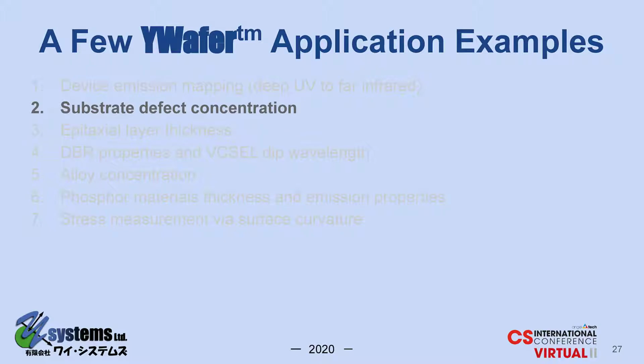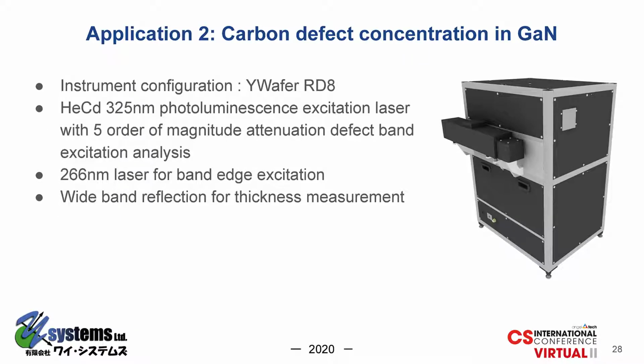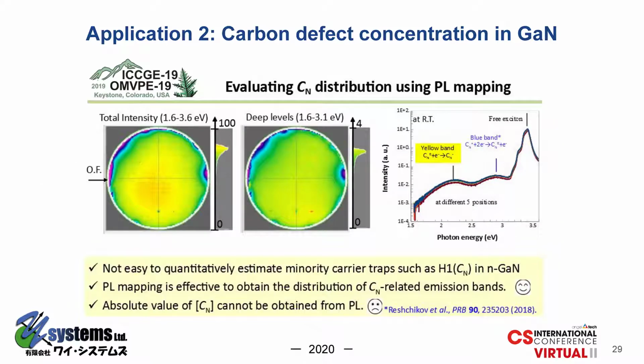Defect concentration is another standard application of photoluminescence. One of our customers has been using a specially equipped RD8 for the study of deep traps in gallium nitride and has shown that PL mapping is a useful tool for run-to-run as well as in-wafer distribution assessment of carbon impurity concentration. Although the conclusion is that quantitative estimates are not trivial, PL mapping is effective in obtaining the distribution of carbon-related emission bands. The results were published last year at this conference in Colorado.